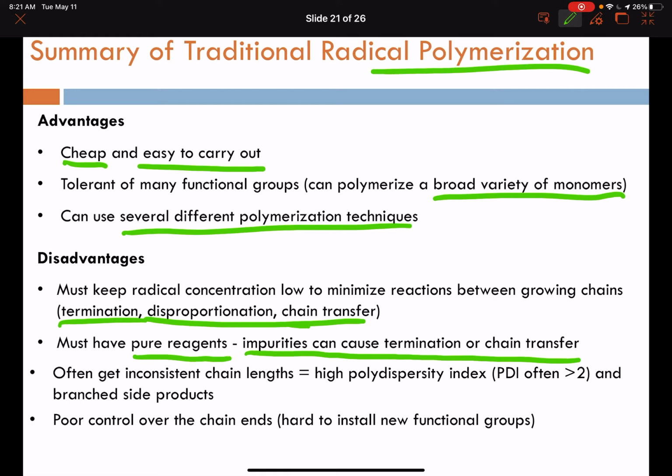And so as propagation is occurring, you are battling against termination, and so you are eliminating the M_n M_m higher molecular weight option as well as any M_n and M_m products by disproportionation. So these unwanted dead chains are being eliminated as propagation proceeds. And if you were trying to target an ultimate molecular weight, you will always be contaminated by these termination products.